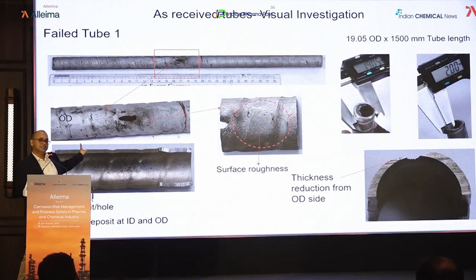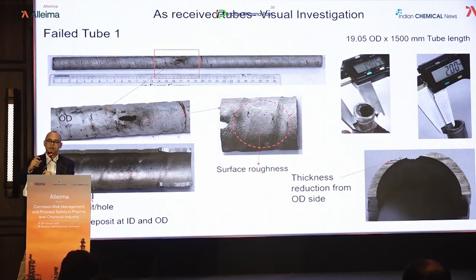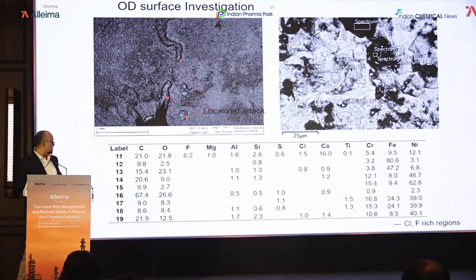But you could still see there is some localized corrosion on the OD side, mostly from the OD side. So in the heat exchanger, basically you have baffle, and if there is something wrong, like if there is some wear between the tube and the baffle, maybe due to vibration, or if the tolerance is not perfect, you can have wear. And then we could see some localized attack also.